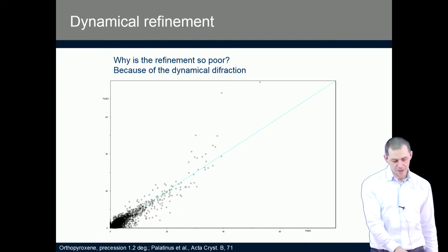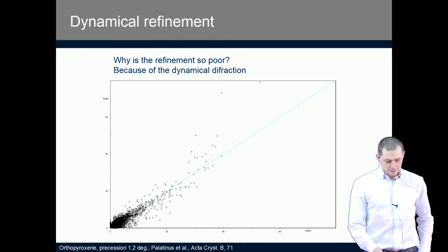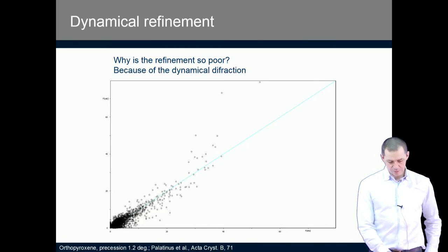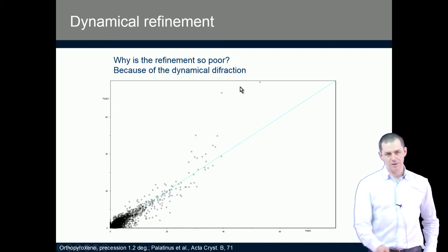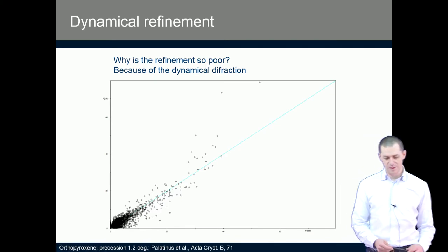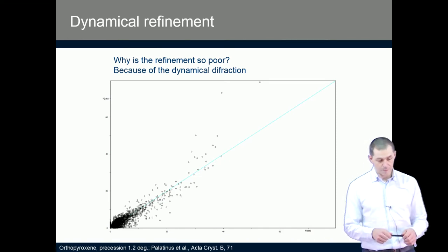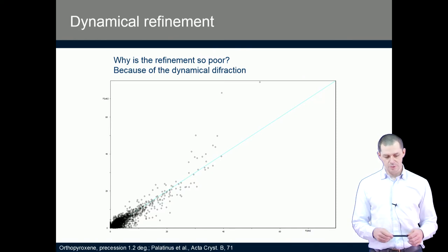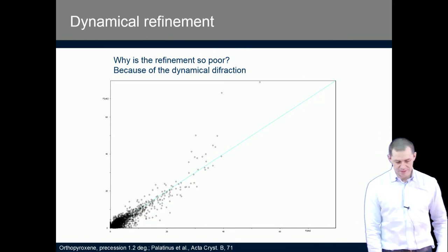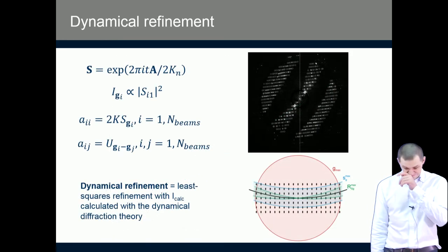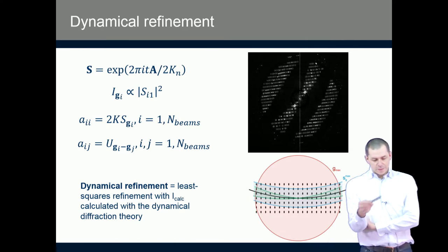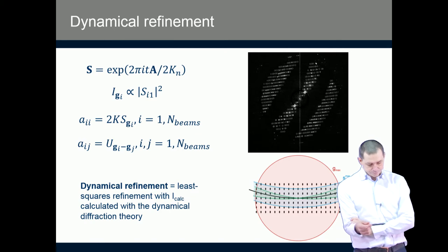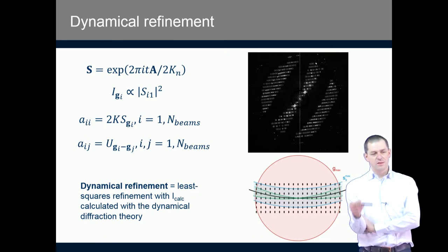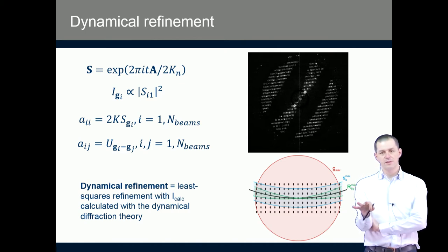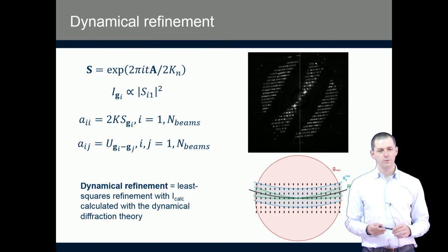And this is the Fobs-Fcalc plot, so a distribution of observed and calculated structure factor amplitudes for the orthopyroxene structure, and you can see a strong deviation, strong scatter of the values around the expected line. And this is caused, or mainly caused, by the dynamical diffraction, which causes the deviations of the measured intensities from the expected kinematical ones. So the dynamical diffraction theory, I just repeat briefly, modifies the intensities, and the intensities of reflections that are simultaneously in diffraction condition are mutually influencing each other.